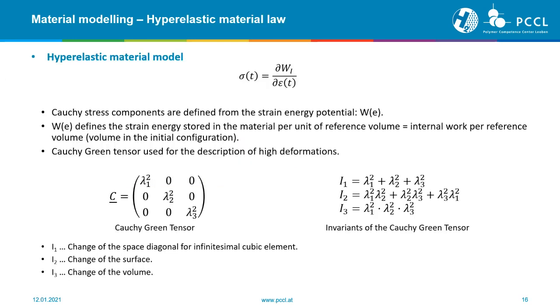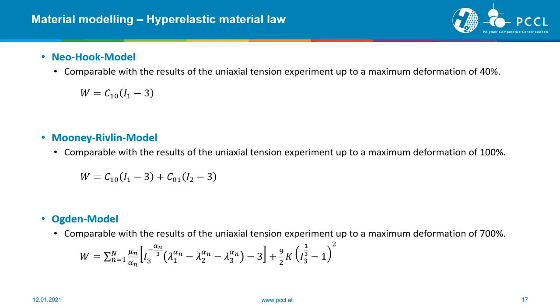When we think of elastomers, then we think of hyperelastic material models, also very simple at the beginning. And here we have to define the strain energy density. This is a specialty of elastomers and of soft materials, that we have a hyperelastic material performance, where the performance of the material is based on an energy, compared to classical polymers. This means when we think of different hyperelastic material laws, which are already implemented in some simulation tools, for example Abaqus, you can choose from a Neo-Hookean model to a Mooney-Rivlin model to an Ogden model, only to give you an example.